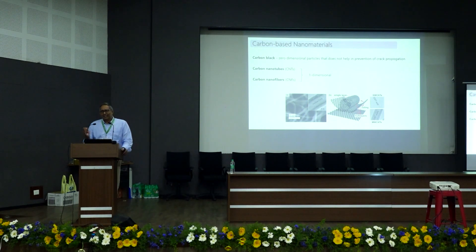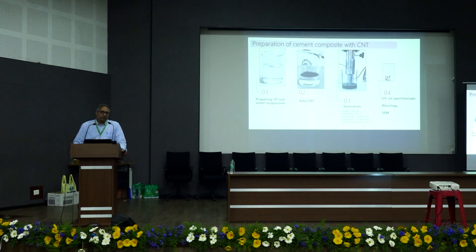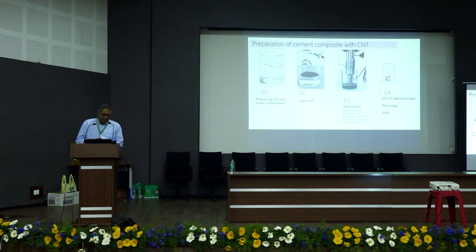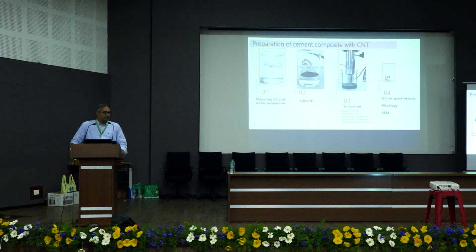The last part of the talk is about CNTs — carbon nanotubes. A lot of people are working on them. One of the key things about use of CNTs is dispersion: because they have a very high surface area, they tend to stick together. If you don't disperse them, you might as well not use them. We have developed procedures to disperse CNTs using a surfactant to get the tubes to separate and ultrasonication to put in energy. You see the glass beaker with water plus a polycarboxylate ether-based superplasticizer to which CNTs are added — they simply float on top like black gunk. The minute you ultrasonicate it, it turns into a blackish ink, meaning the CNTs have completely dispersed.